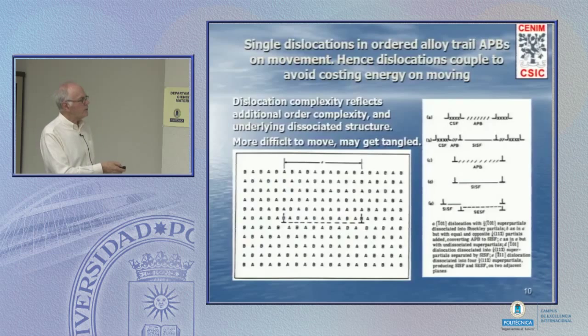And what we've seen is that here's an AB ordered matrix. Here's the one dislocation, and ABAA. This is the disorder behind it. What do I do? I couple the one dislocation with a second one that repairs the order. And this is the super dislocation.